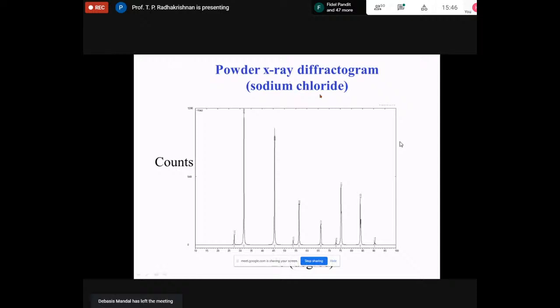And if you remember, I mentioned this was the first structure looked at by Bragg and Bragg. You get these very nice sharp lines at specific angles. Now, why specific angles? Because only at that particular angle it satisfies Bragg's equation, and you get strong X-ray scattering. At all other angles, there is no scattering and nothing comes out. Now, curiously, some are very weak, some are very strong, and there is something in between, and so forth. There's a lot of variation in the intensity.